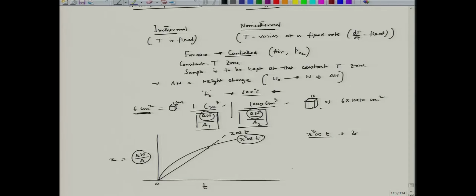So, in case of zirconium, or at a low thickness of oxide, we can also have a logarithmic law, which is indicated by x proportional to log t, or x equal to a log t plus b, where a and b are constants. This is valid for a system, for example, in case of iron, it will be experienced at a low oxide thickness. We experience this kind of rate law. This is cubic, this is logarithmic, fine. So, these are the possibilities.